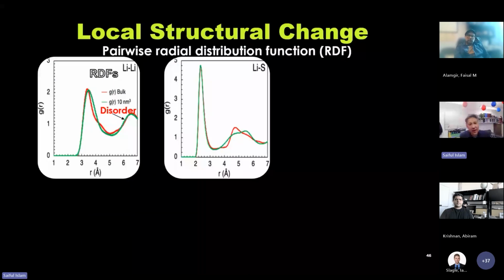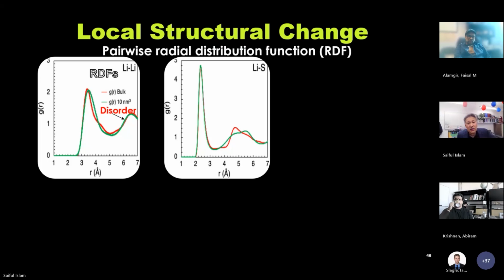What I'm showing you here is some radial distribution function, RDF, which is a bit like pair distribution function analysis from experiment. On the left is the lithium radial distribution function. In green is the nano material, and in red is the bulk material. Very similar, but after the first peak, there's some broad peak suggesting quite a bit of disorder in the lithium-lithium sublattice, which is true. You're getting fast, liquid-like lithium-ion conduction for both bulk and nanoscale.